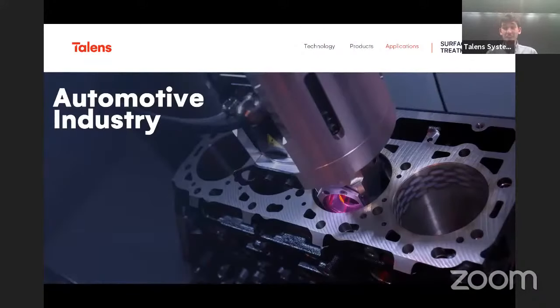We have different types of applications inside the automotive industry. Right here, you can see one specific application we are developing for a very specific big OEM in the United States, where we are laser hardening cylinder blocks inside, and only those areas that you can see over there. It is a very specific geometry where we are laser hardening with a case depth of around 400 to 500 microns, in very specific areas.